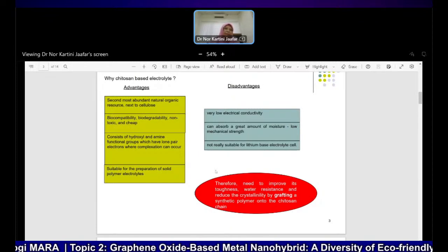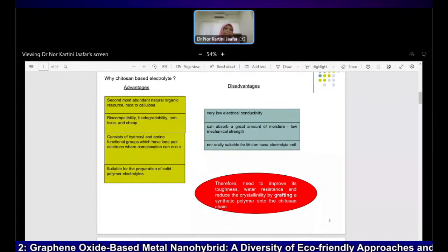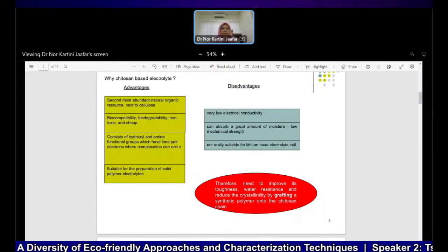Scientists before also showed that Chitosan has hydroxyl and amine functional groups that can coordinate with the salt, and it is quite suitable for the preparation of solid polymer electrolyte.